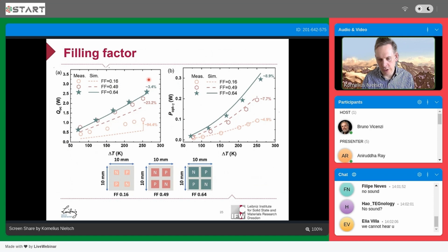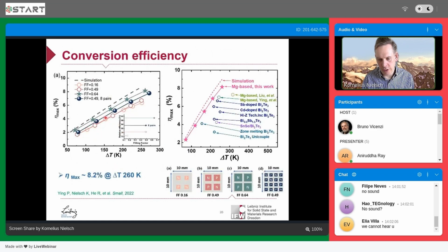And you can see it in this right plot. So we obtained nearly 9% efficiency by using, for example, the densest device with a 64% filling fraction. And also the power output of the whole device significantly improved by using this denser placed device. So the maximum performance was about here, 8.5%. We had a temperature difference applied of 260 degrees.